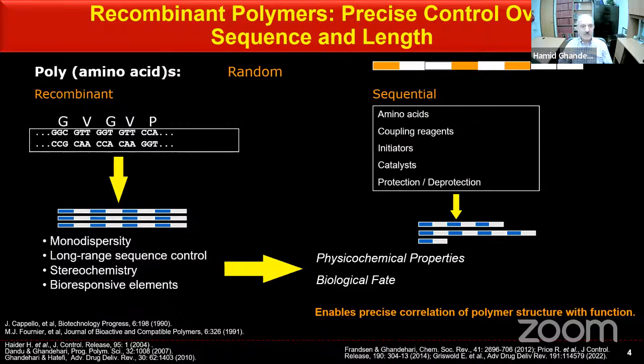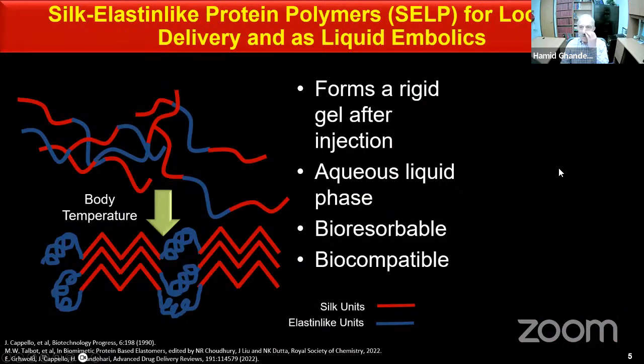I'll show you one example later where we have put MMP-responsive sequences at strategic locations in the polymeric backbone. And as a consequence, you can have a better control of the structure, which leads to better control of the function of these materials. So one of these polymeric materials that we have worked on, which I will show you the structure in a second, are the so-called silk elastin block copolymers.